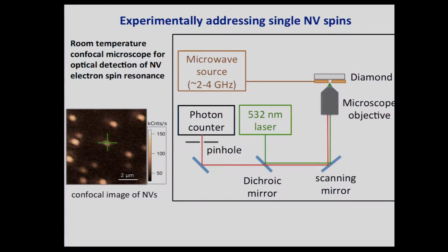To address NV centers, we optically address them, but we also perform optically detected magnetic resonance, which necessitates a means by which we can deliver microwaves, about 3 gigahertz microwaves, to our sample, which we do by patterning the diamond, or the glass which the diamond sits on, with waveguides. And then at that point, we fix our laser on one spot, and we drive a set of microwave pulses that we have drawn from the NMR community back in the 50s in order to exert quantum control over the NV center and do sensing in that way.